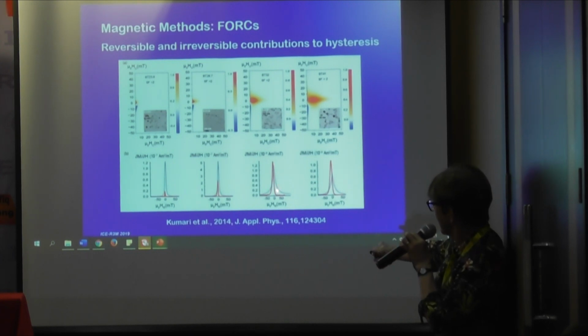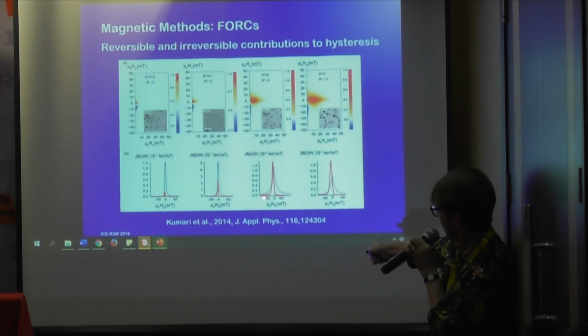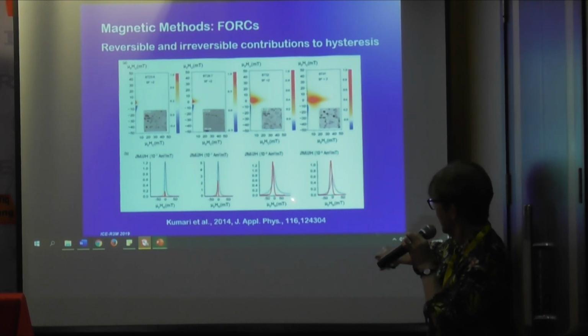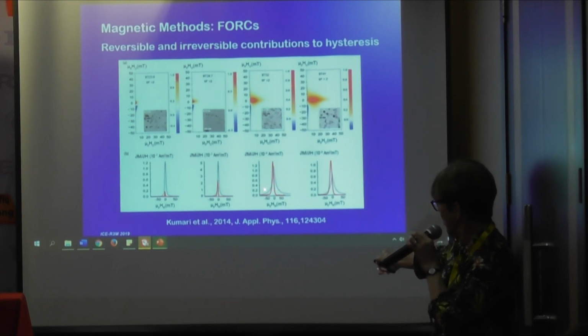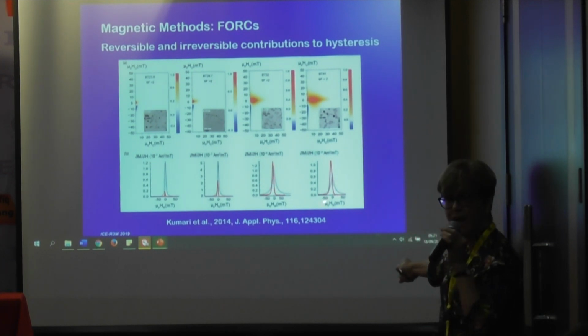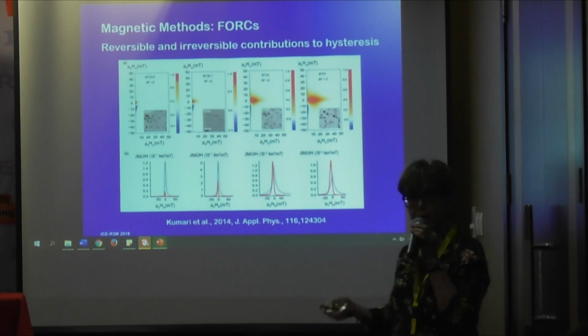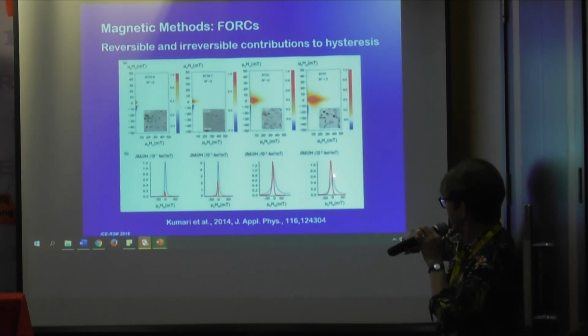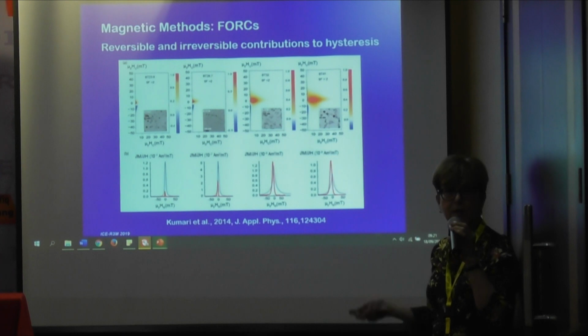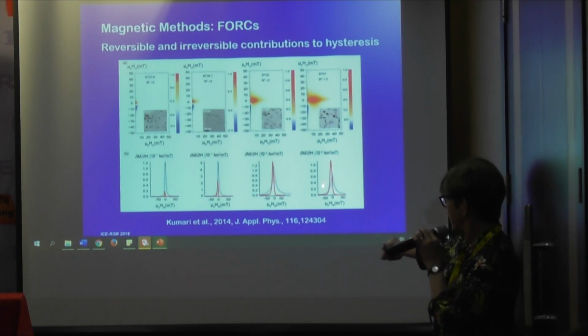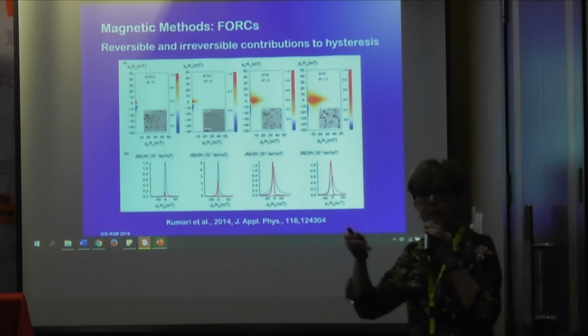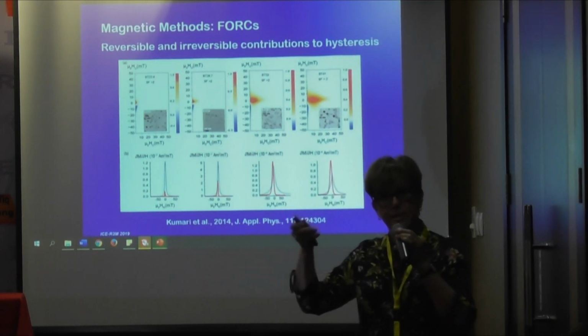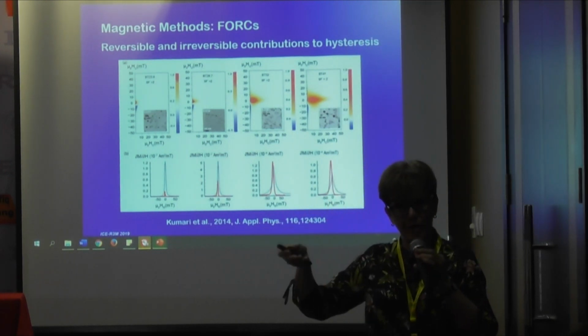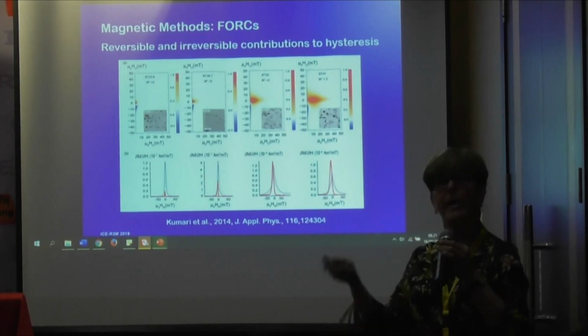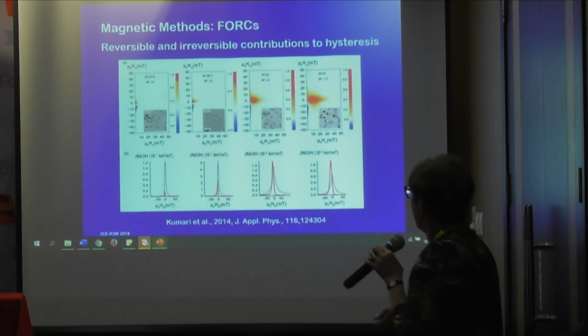So in this case, what you see is the reversible part of the signal, the blue curve, and the red curve, the irreversible. And here, in this case, both are similar. What I should have said here, in the ideal case of single domain, you would expect the reversible part to be 50% of the irreversible part. And so this is a beautiful example where I say physics works. This is the theory, it says this is what you should get. The reversible part should be 50% of the irreversible part, and it is, so that's great.